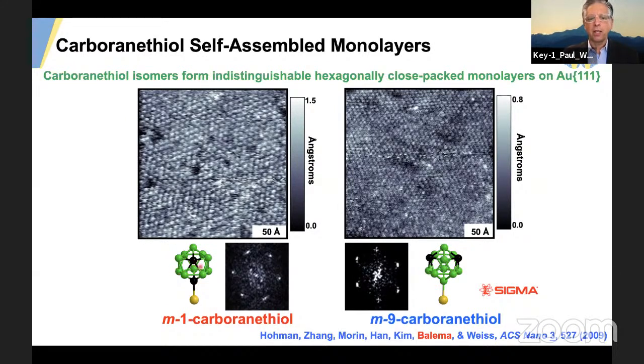So here, since the carbons are effectively on the side, we end up with a neutral surface and dipoles in the plane of the surface. Here, since the carbon atoms are on the exposed end of the monolayer, we end up with a positively charged surface. And one of the neat things about these cage molecules is that their lattices are determined by the projection of the cage on the surface. So all of this family form identical structures.